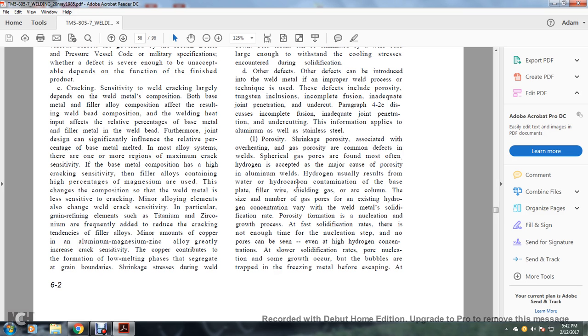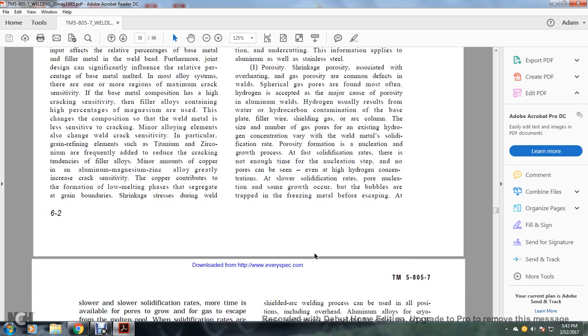Hydrogen usually results from water or hydrocarbon contained on the base plate, the filler wire, the shield gas, or the arc column. The size and number of the gas pores vary with the existing hydrogen concentration and the welding conditions. Solidification porosity formation involves nucleation and growth processes, with fast solidification rates leaving not enough time for the nucleation step. No pores can be seen, and even at high hydrogen concentration, a slower solidification, pore nucleation, and some growth occur, with the bubbles trapped in the freezing metal before escaping.